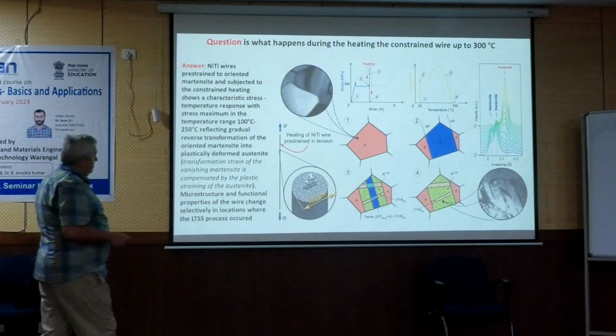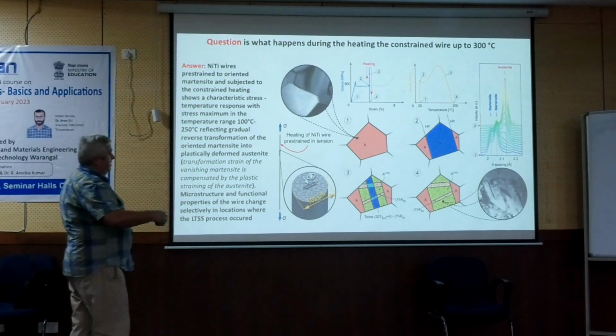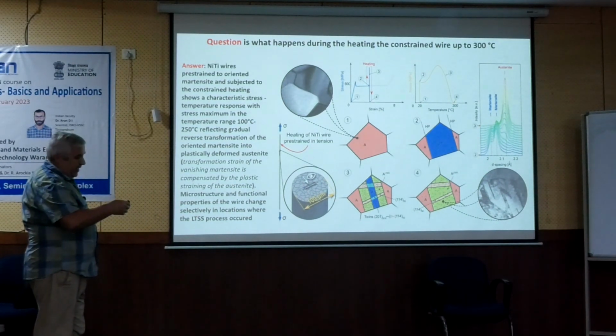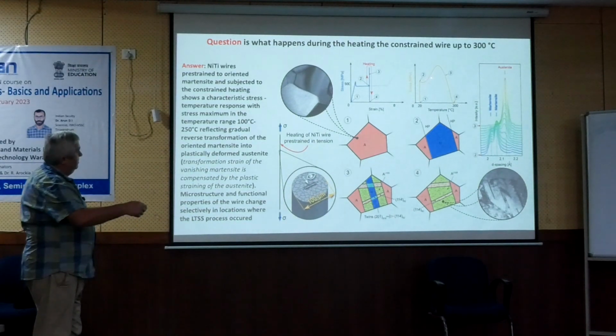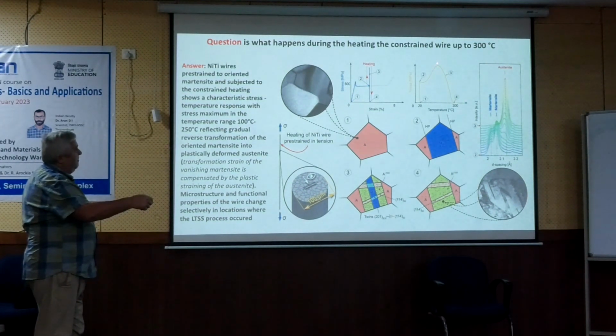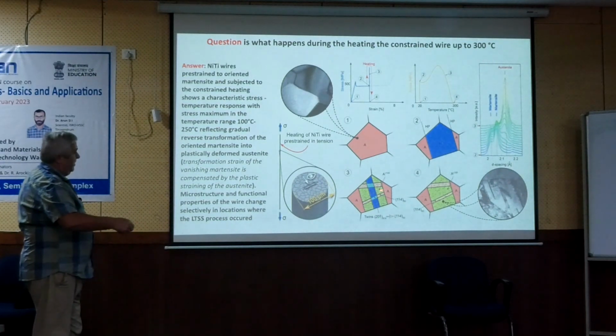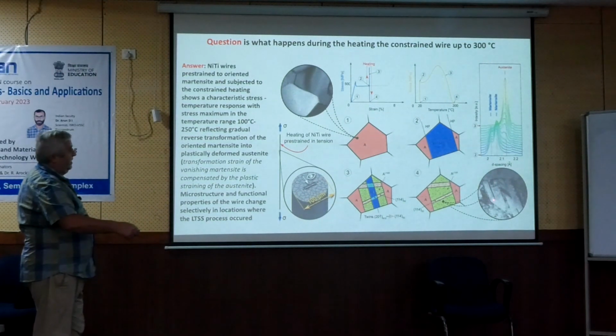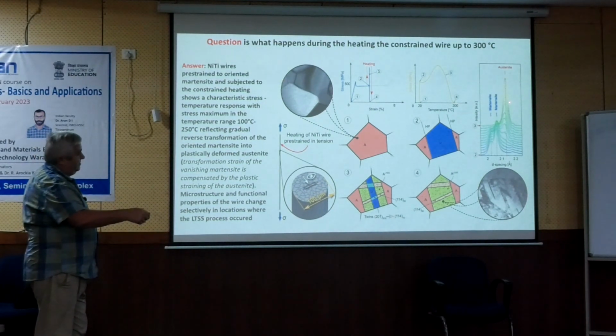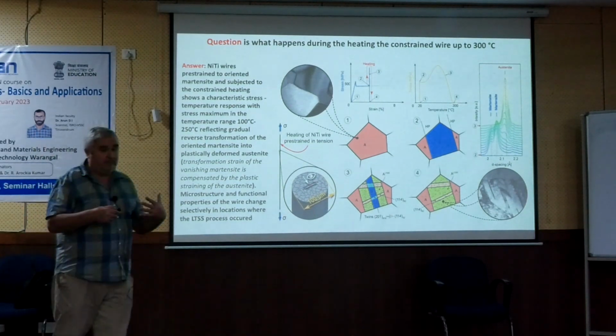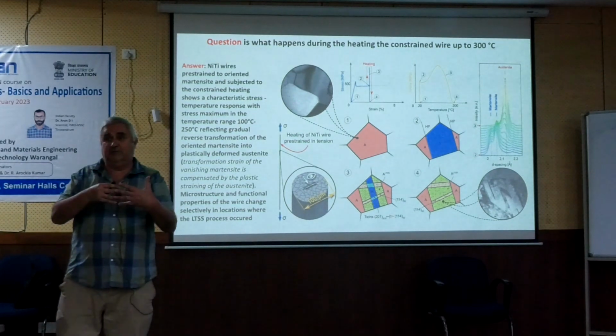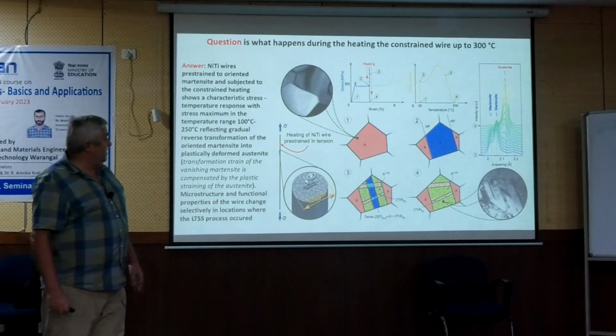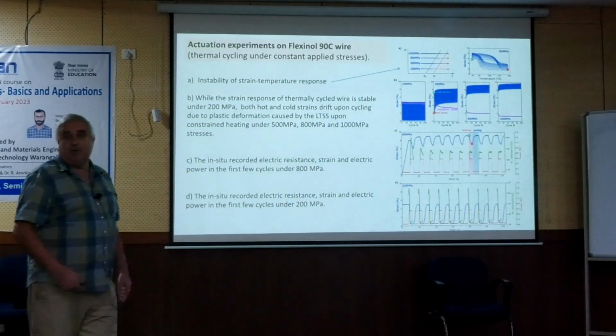So this scheme explains how we understood this shape setting behavior. If you are in the martensite, plastic deformation of martensite via kinking is created. You will have these kinks, and this is what we observe in the microstructure. And during this process, we see how the martensite is converted to the austenite. So the experiments give very solid evidence about the process which occurs upon heating. So with this one, I am probably at the end.